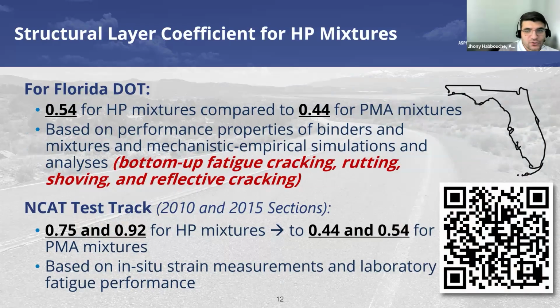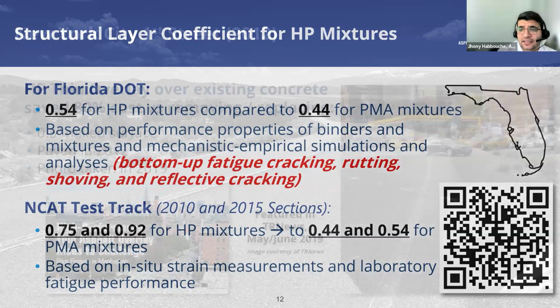Back during my tenure at the University of Nevada, Reno, we led a research effort for Florida Department of Transportation, trying to give them guidance on what structural layer coefficient they should adopt for high polymer mixes. It turned out to be 0.54 compared to 0.44 for their conventional PMA. This was performed taking into consideration several material characteristics, aggregate and binder, multiple distresses, and various pavement structures, and done based on mechanistic-empirical simulation. I'm not going to cover the NCAT test track. Nam covered that in detail.